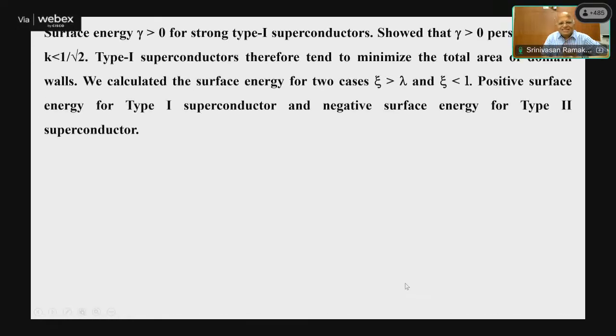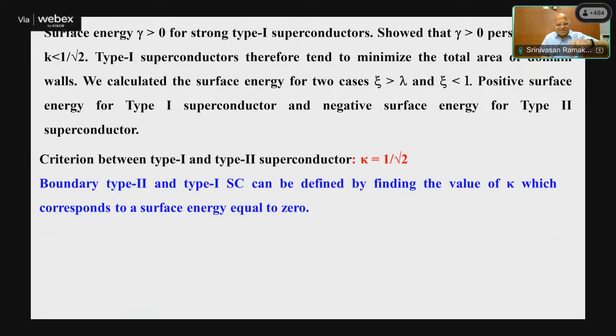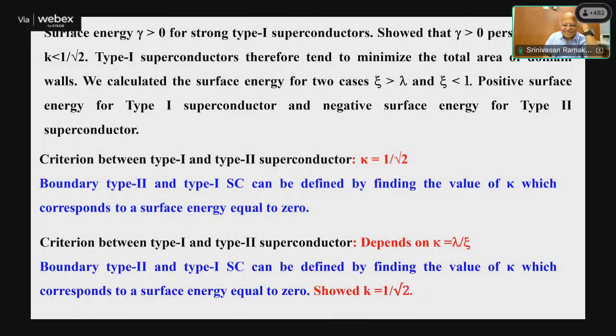So the surface energy is, as I said, strong for strong type 1 superconductors. And Ginzburg-Landau showed that it persists for all kappa less than 1 by root 2. So type 1 superconductors tend to minimize the total area of domain walls. So one can do the surface energy for xi greater than lambda and xi less than lambda. So you can have a positive surface energy for type 1 superconductors and a negative one for type 2. So as I said, kappa sits at the edge. When kappa is less than 1 by root 2, it's a type 1. Kappa greater than 1 by root 2 is the type 2 superconductors.